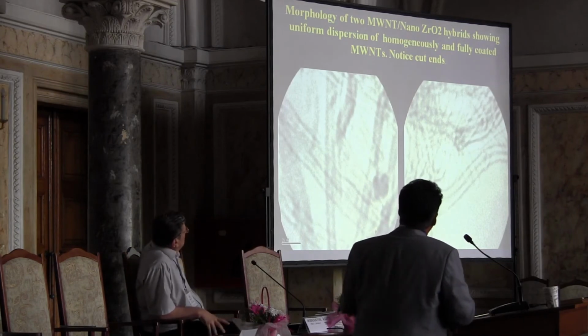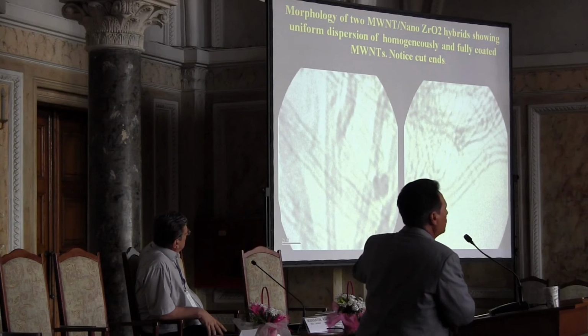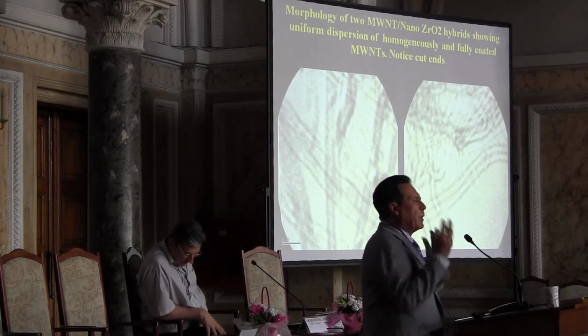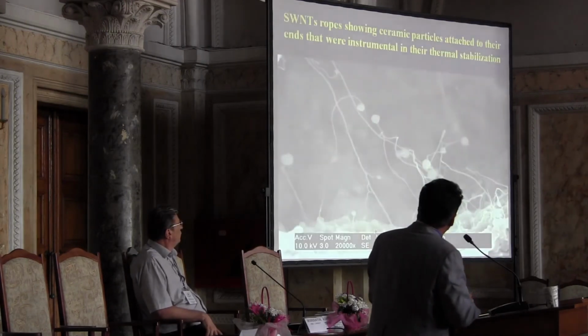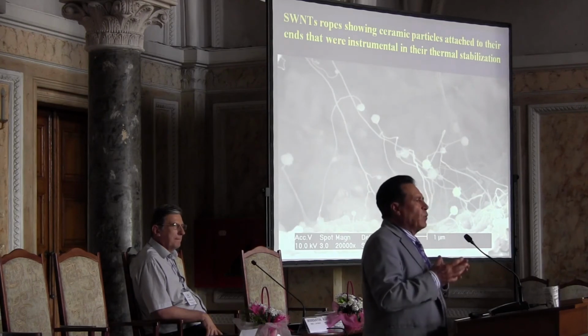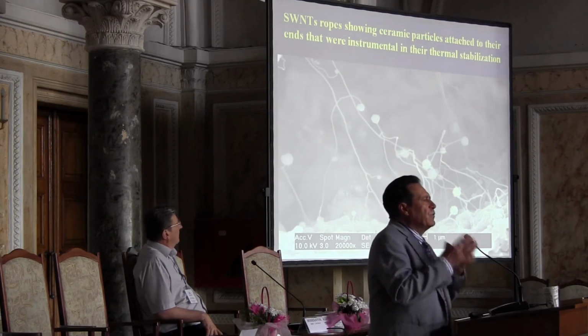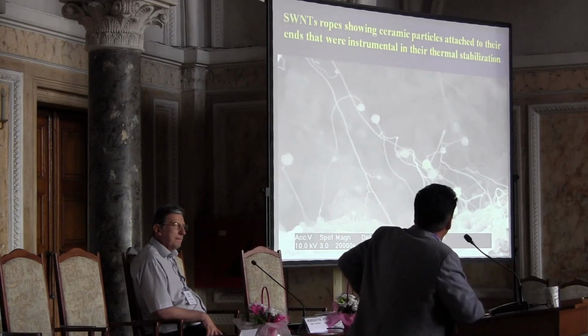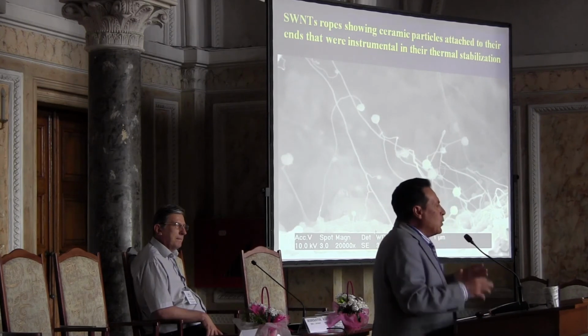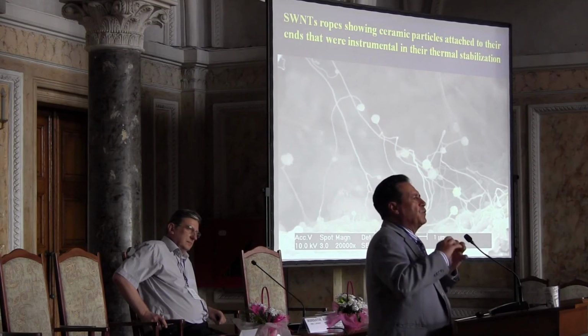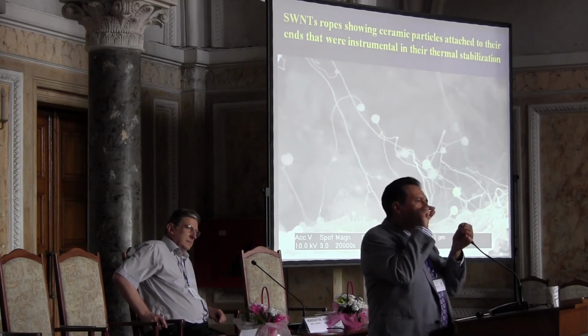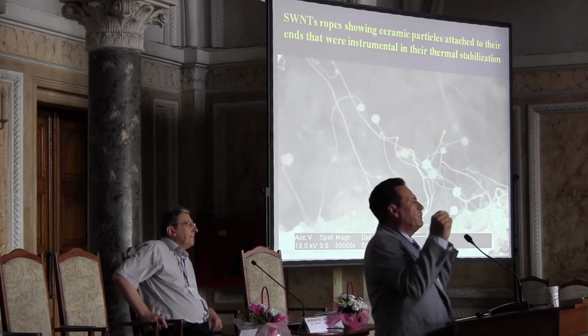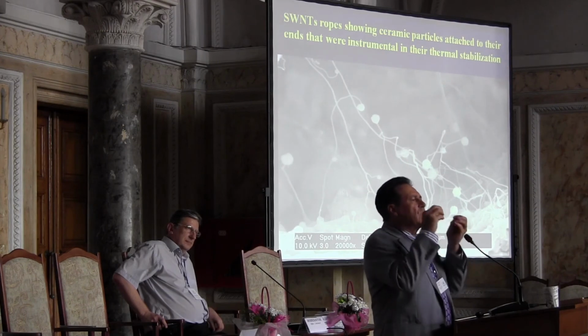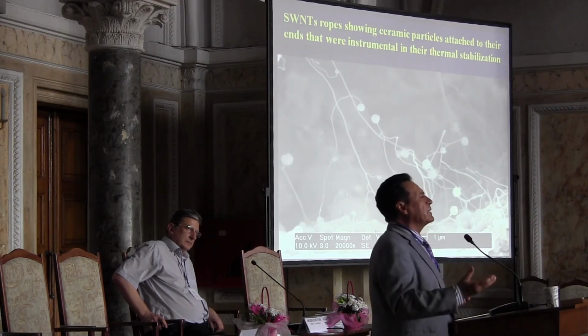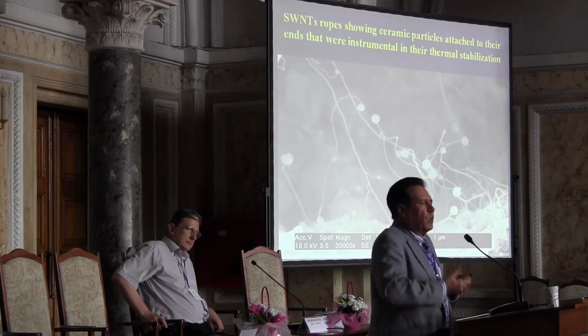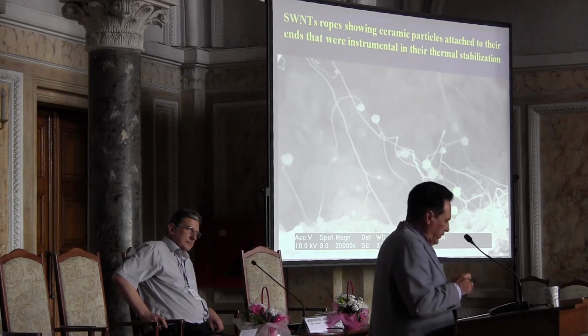Okay, so basically what I'm showing in here is that you can functionalize these carbon nanotubes and coat them completely, and then integrate them in these matrices. And of course, you are saying, well, what is the thermal capability of this carbon nanotube in a ceramic matrix? Well, it can go up to 1400 degrees C, because when we coat these carbon nanotubes with this nanozirconia, the defects in the ends of the carbon nanotubes and all the defects are plugged by these particles, and these particles stabilize the carbon nanotube, giving us the possibility of sintering and consolidating these materials and having the performance at very high temperatures.